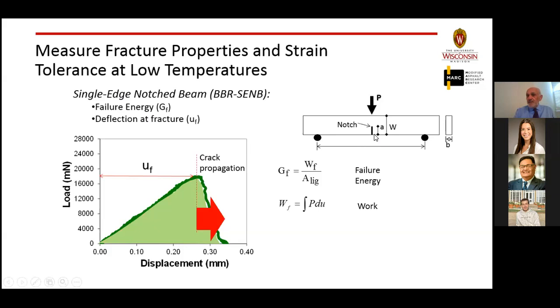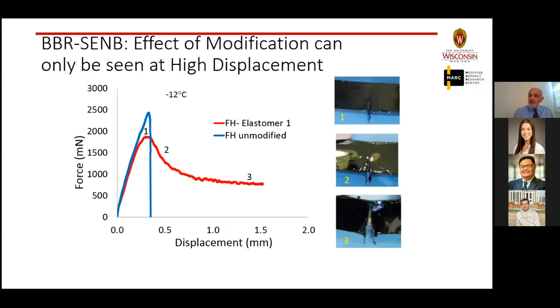And the reason I'm showing this test is to show you that if you're here, you can tell very little about what happens here, particularly when you start the crack propagation. But if you continue to load your sample until you get into the crack propagation, I think you will find a very interesting behavior that could actually give you a better tool, and I would say much more information to pick the right binder. Here's an example.